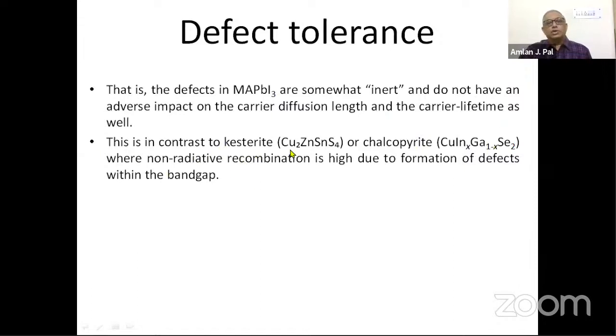This is in contrast to other conventional compound semiconductors, where the non-radiative recombination is high due to the formation of defects within the band gap. In CZTS or CIGS materials, the defects form within the band gap. As soon as the defects form within the band gap, the carriers will become trapped. If it is below the conduction band, the carrier will be trapped at the defects, and then carrier transport will be stopped.